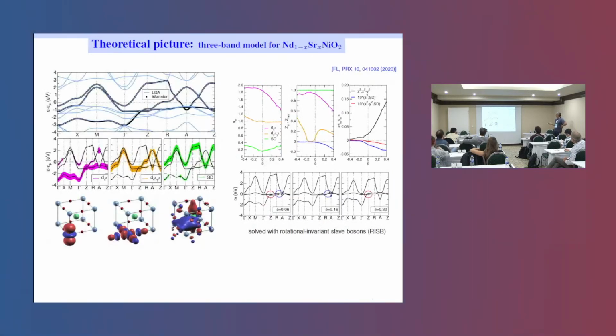So then from this basic picture, let me speed up, we do a minimal modeling. We take out these 3 contributions that we think are important: the nickel x squared minus y squared, of course, the nickel d z squared, and some self-doping band that is always there, at least at the geometry. We do an effective 3-band modeling with some simpler than DMFT scheme, and we get the same picture.